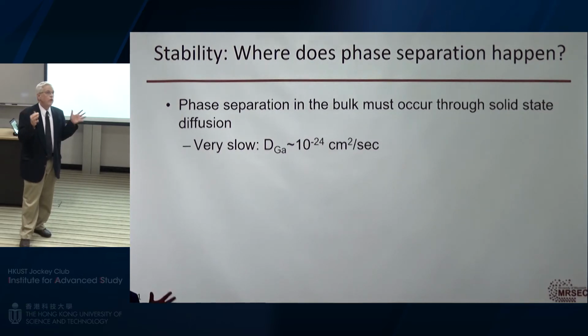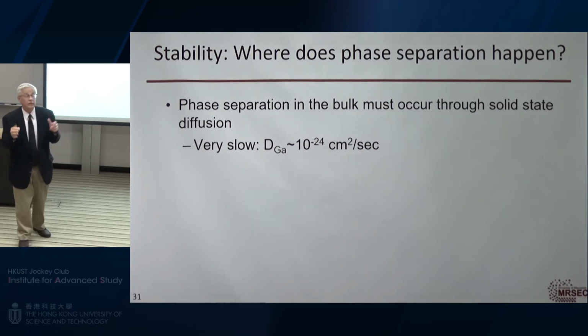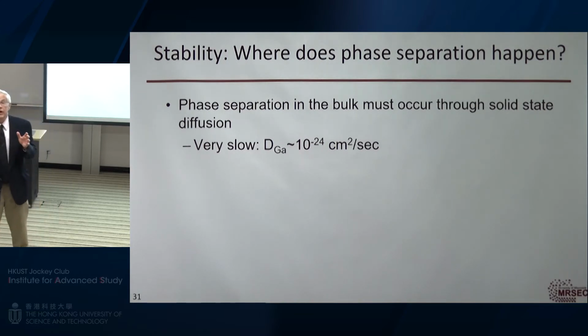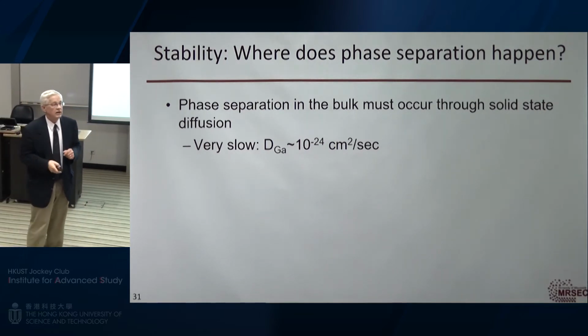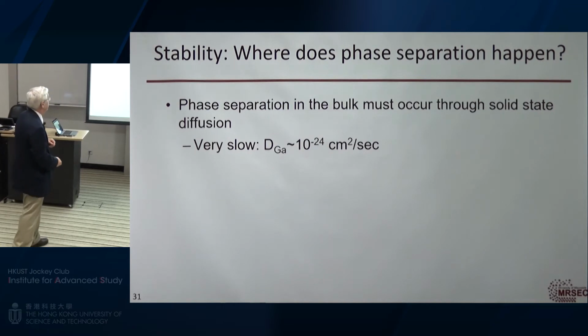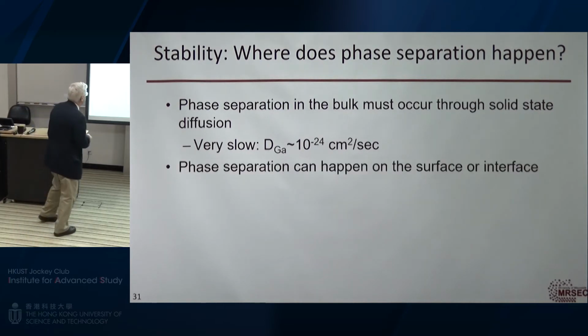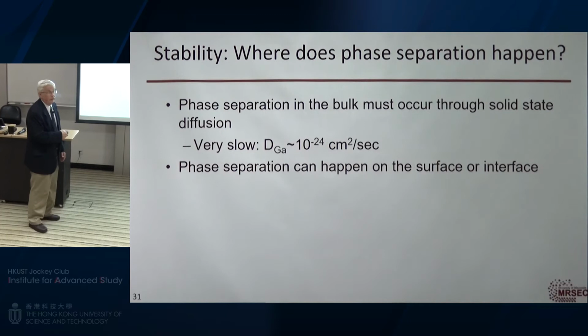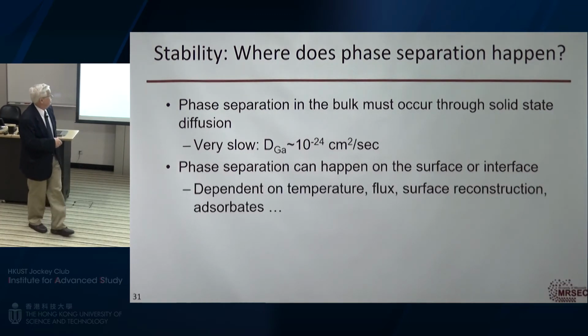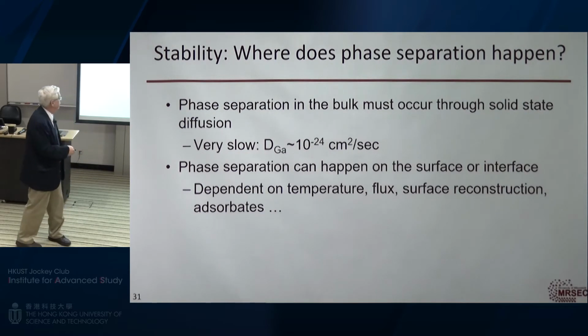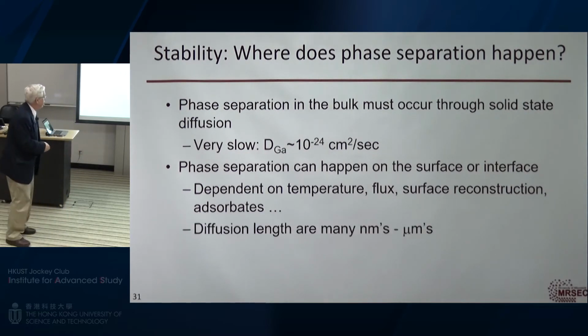So the trick is, how do I put the atoms together in the right structure? Because once I do that, even though it wants to fall apart, it has no kinetic pathway that's viable. So phase separation actually only can happen at a surface or an interface during growth. And that's dependent on the temperature, the flux, the structure of the surface, what's adsorbed on it. Because on the surface, atoms can move a great distance at high temperature.